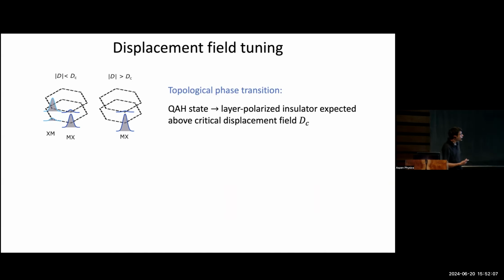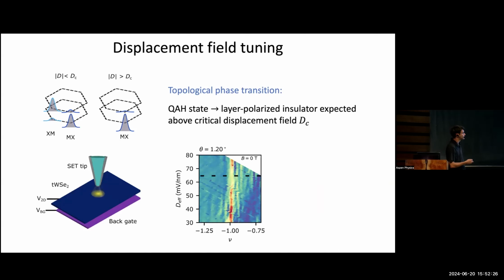We can go one better. We can look at how the displacement field affects the behavior of the state. There's a prediction that there's a change from this symmetric case where you occupy both XM and MX sites to a state that's favored in the presence of a displacement field where you preferentially occupy just one of these layers. And we can use our tip to locally gate the sample. And in doing so can then effectively modulate the displacement field.